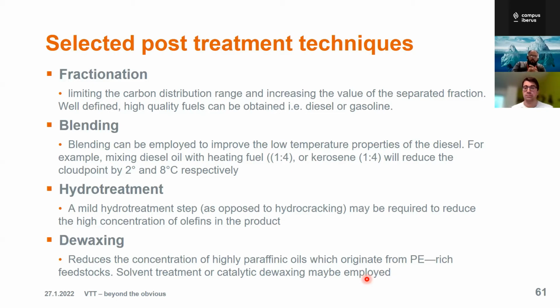Hydrotreatment means you can basically use hydrogen to reduce the concentrations of olefins or saturate the olefins in the product. Dewaxing, I told you about. If there are waxes in the pyrolysis oil or components of the waxes, then you can crack the waxes using some solvent treatment technique or using some sort of catalytic means for cracking.